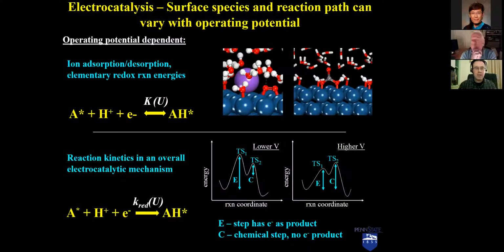But in our chemical system, we expect that these equilibrium constants and rate constants will depend on this variable voltage or potential, the operating electrochemical potential set in our electrode by our electrolysis or fuel cell device. And that's because that potential is embedding the energy of the electrons being involved in the reaction. So if we're adsorbing, say, a cation, a proton from solution onto our surface, then the energy of this electron is going to dictate equilibrium. If we made our surface more negatively charged, the energy of our electron higher, we're going to drive this reaction to the right. And we need to be able to express how that equilibrium depends on that voltage.